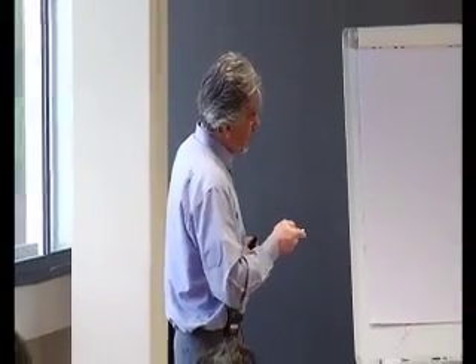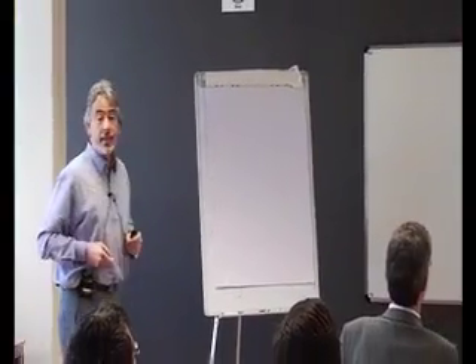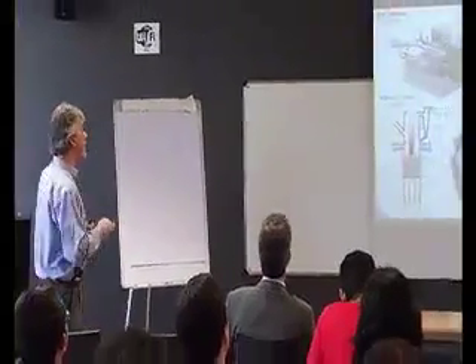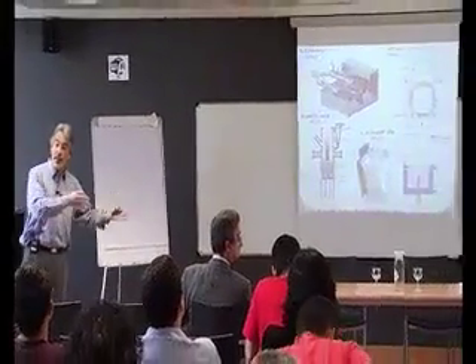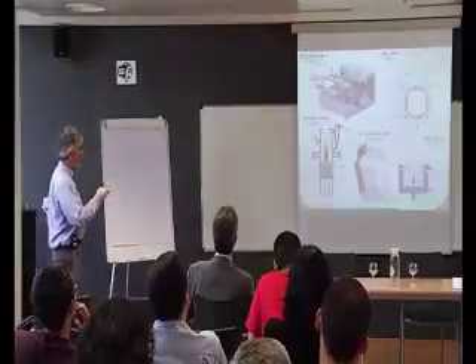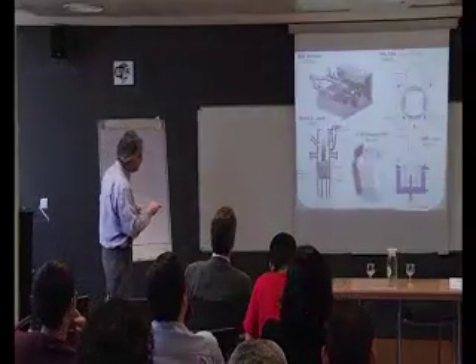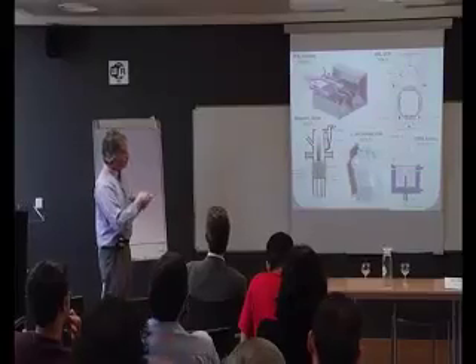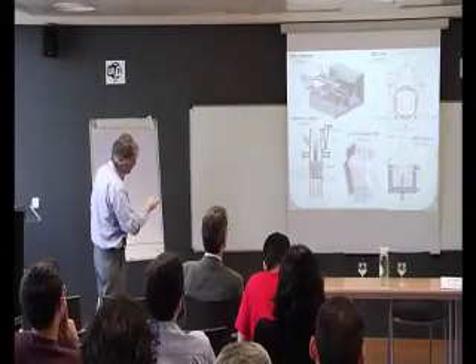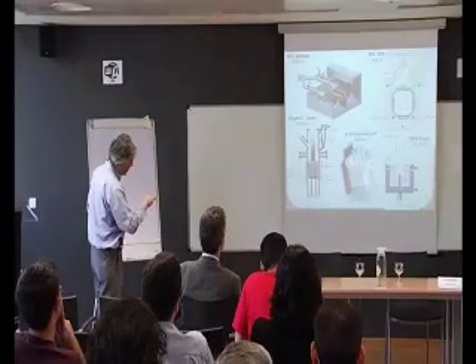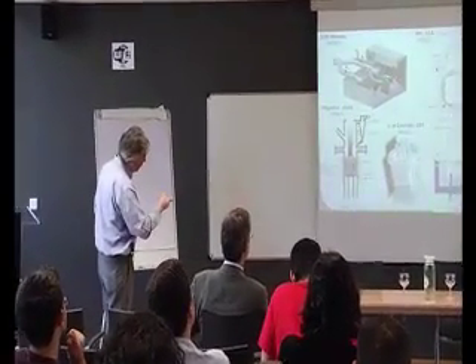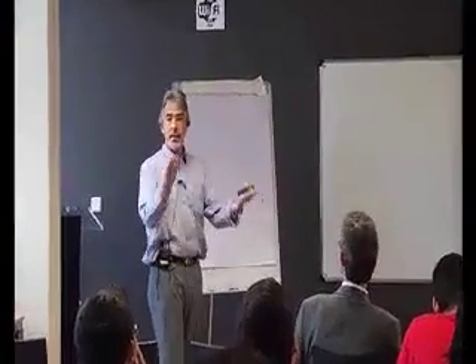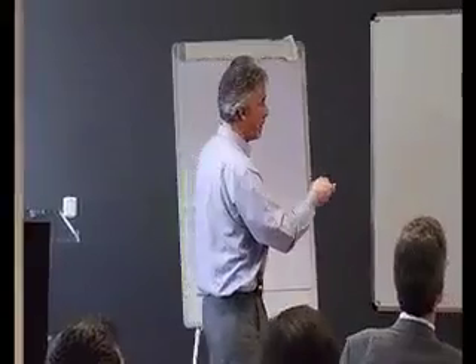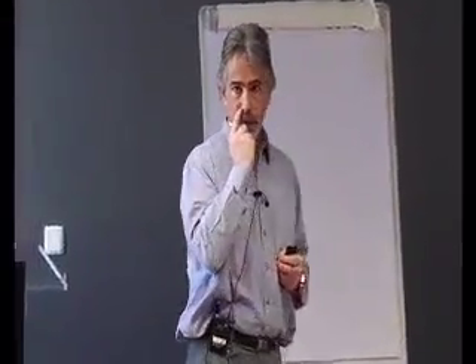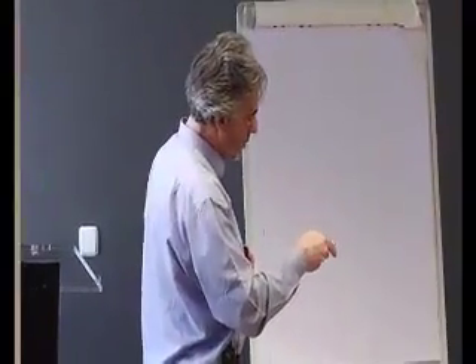Here in the corner you see the solar reactor that is being developed at DLR. They are using a cycle which is based on zinc ferrites, so it's reduction and oxidation, and the reactive material is zinc ferrite, and they use two monolith reactors, one next to each other. While one is undergoing the hydrolysis, you see the steam reacting. This is the oxidation step. The other one is undergoing the reduction. And then once this is done, you switch the flows. Then you will have reduction here and oxidation here. And of course there is a temperature cycle, because the reduction is at higher temperature, the oxidation is at lower temperature.